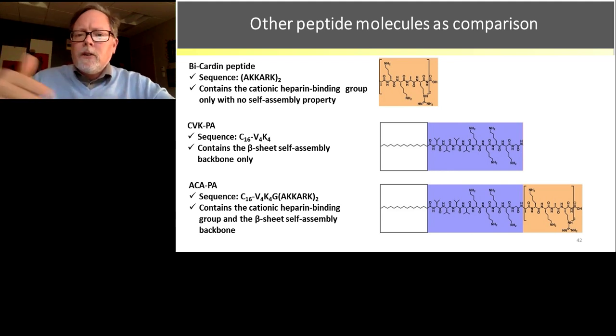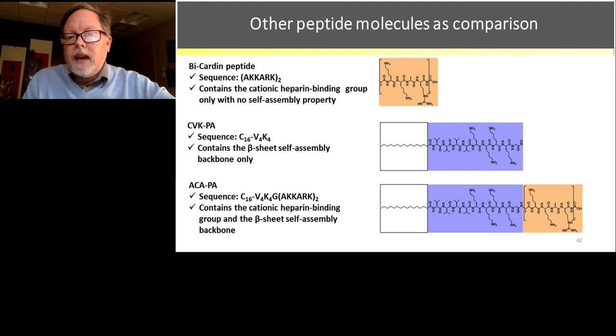So we created our material step by step, and we added it to bacteria. The first step was just this Bi-Cardin peptide. This orange region, as I mentioned before, is the peptide that targets the cell membrane, the bacteria cell membrane. So we used that as one material. Another material we call CVK-PA. This is really the beta sheet self-assembly part. So we added that just to the peptide. That was our second material. Our third material is the whole entire thing. So we now have the hydrocarbon backbone, the beta sheet formation, and that region that attaches to the bacteria membrane. And as you'll see, it's all three of these together, the ACA-PA, that works. If you remove any part of this three-component system, the whole thing doesn't work and it doesn't kill bacteria.